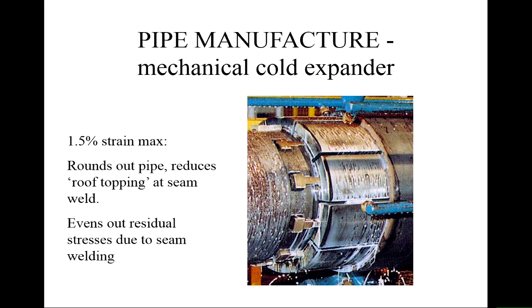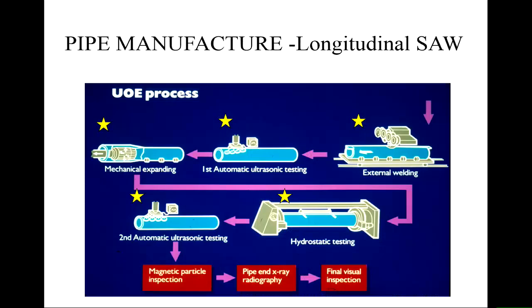When you weld, because the weld in an arc weld is not totally parallel, it has a V shape, then you get different amounts of thermal expansion at the top and at the bottom of the weld. You will tend to get distortion due to the different stresses that generates, and that will actually lead to a failure if you're not careful. And certainly it will make it difficult to match pipe segments up. You want them to be perfectly round, so the expansion process is good for doing this.